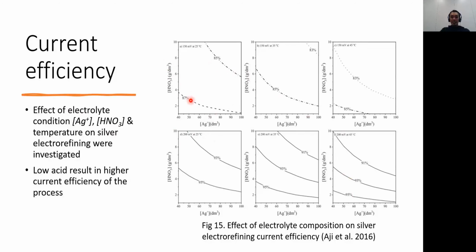As we can see here, with the increase of nitric acid, the current efficiency just drops, from 87%, shown by this iso-efficiency dashed line, to 85%. And an increase of silver content actually also decreases the current efficiency. It's quite interesting, but that is the result that I got from the measurements. So in this sense, to have very high current efficiency, we need to reduce the nitric acid content, and it's also safer to reduce the silver ion content.